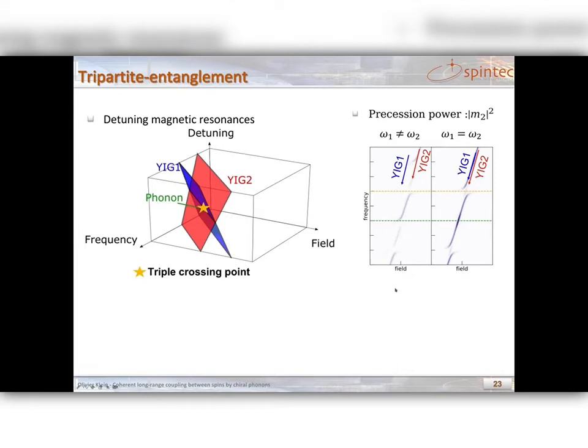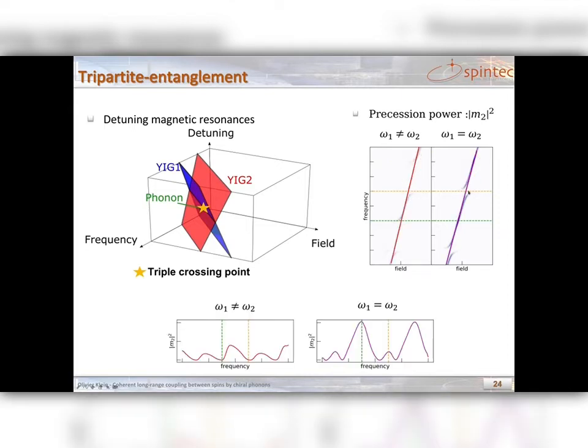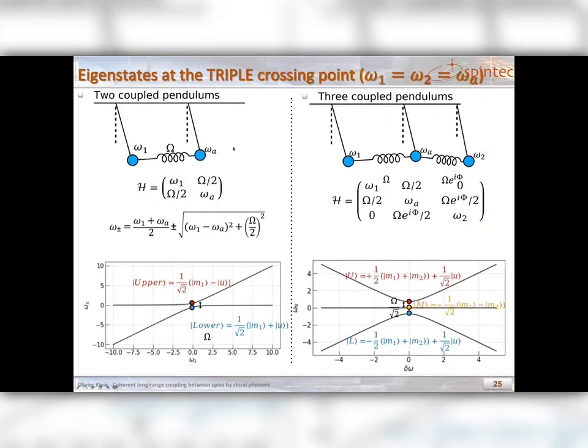Here is the calculated power absorption by YIG2, and what we can see is overall, the power absorption increases at the zero detuning on odd phonons, while it completely disappears at the zero detuning with even phonons. If you look at the line cut, okay, what you see is that before, the maximum was located between phonon lines, and here at the triple tuning, the maximum is located at the phonon lines. So to understand better, we look at some analytical expression.